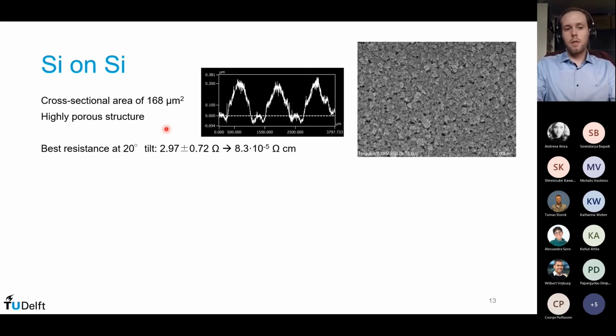So the lines have a cross-sectional area of roughly 168 square micrometers, which is quite good. It's more or less the minimal size that we need. We don't want to make it too thick because that will cause additional stresses. And you don't want to make them too thin because then your electrical performance is too low. So this is, I think, a fairly good compromise. This also makes sure that any surface morphology problems like hills or sharp corners can be crossed effectively. And the structure is highly porous, as you can see in the SEM image on the right.